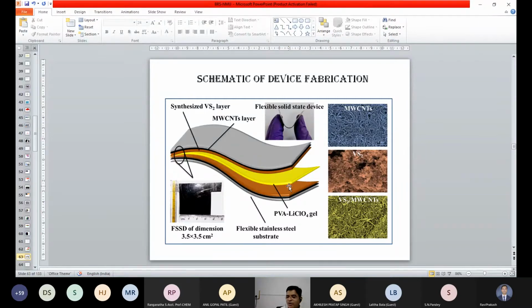Now you can think, what is the dielectric media? Because for a capacitor or supercapacitor, we require a certain dielectric media, right? So here we have used a certain polymer called polyvinyl alcohol. This is a non-conducting media, right? And we have made a gel, that is LiClO4 dissolved inside the PVA. That is the conducting electrolyte dissolved in a non-conducting media, so that it forms the matrix embedded with the conducting ions, and that we have put in between the two electrodes. That is sandwiched by using this gel between these two electrodes.